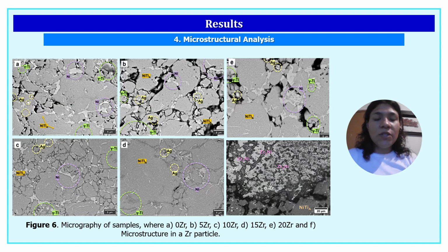The microstructural analysis showed a matrix composed of the austenitic nickel titanium phase, along with remnants of pure nickel and silver at the grain boundaries. The microstructure of the gamma titanium phase was also observed. Inside a zirconium particle, the characteristic microstructure of the zirconium-2 nickel intermetallic was observed, surrounded by alpha zirconium phase.